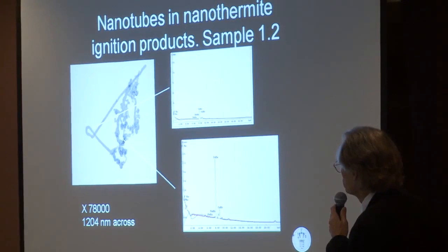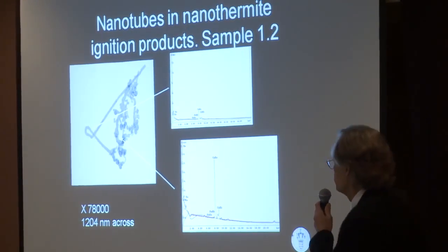What you can do, luckily, we can do energy dispersive spectroscopy very locally on this sample, taking on this bend here. I know it's hard to see. I haven't had time to do good plots. So let me tell you, what you see here is carbon only, and then you see copper, but this is because they're lying on a copper grid. So this is background, nothing else. Most importantly, we do not see any fluorine, because the plastic that Kevin used for making this preparation contains fluorine, meaning that this is not plastic threads.